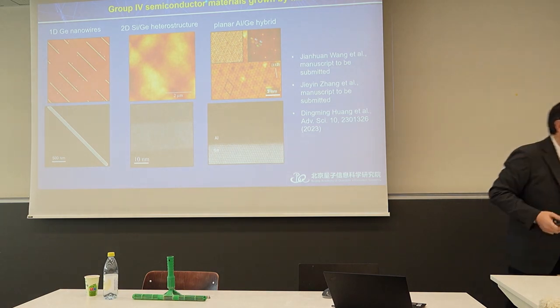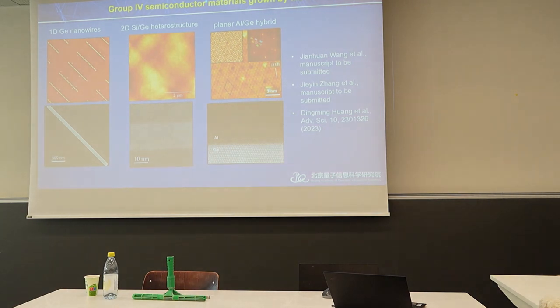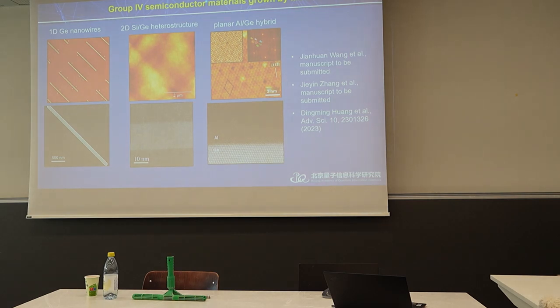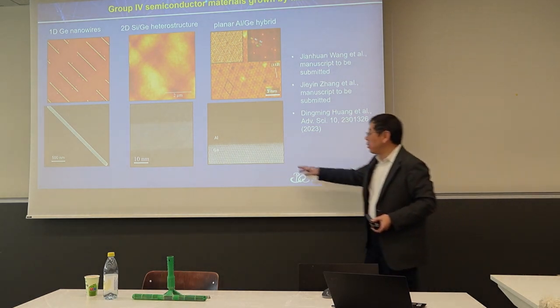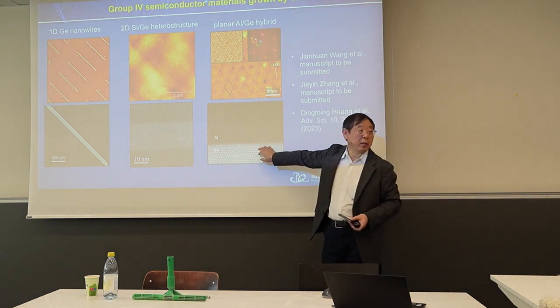Maybe just a question on when you grow the aluminum layer. Do you grow it at room temperature or at cryogenic? It's low temperature. We don't know how low because we don't have it in this machine yet. We don't have a very good sensor for temperature, but it's below 0 Celsius. So we try to go as low as possible with nitrogen, helium nitrogen vapors circle. And we will build a new MBE to make better control.